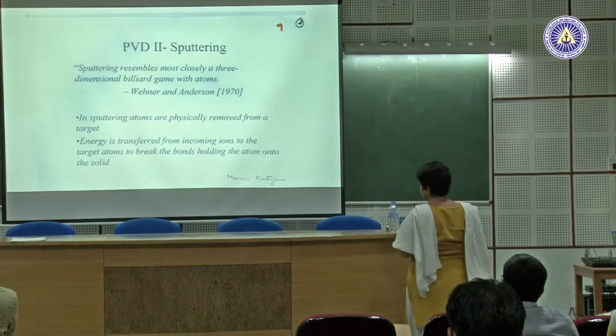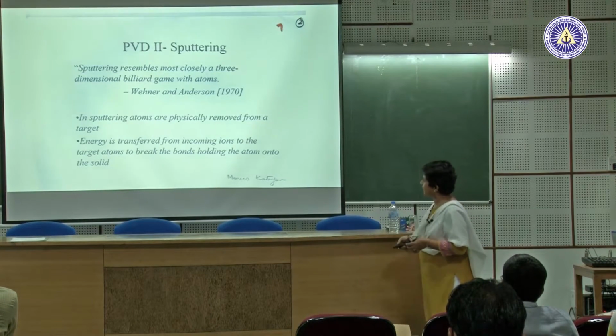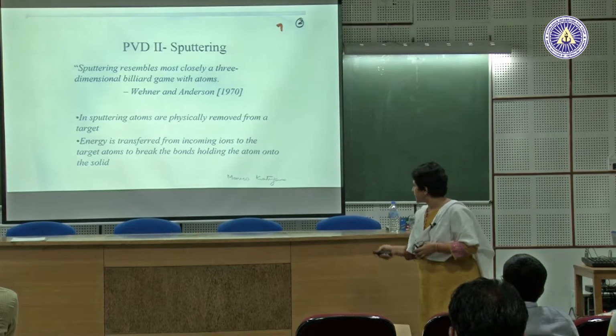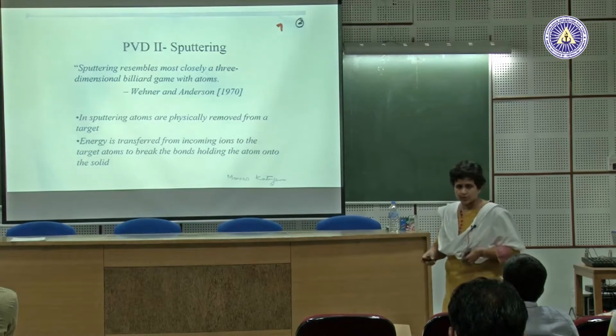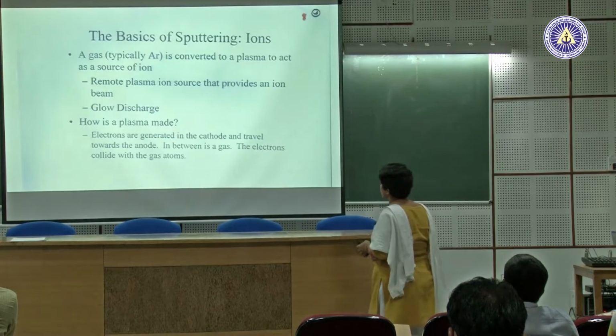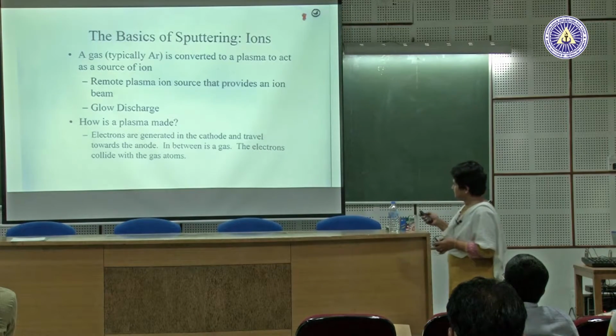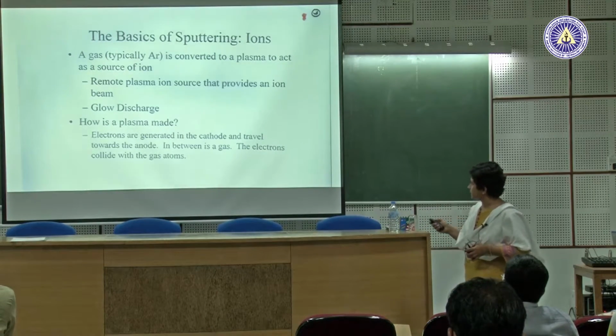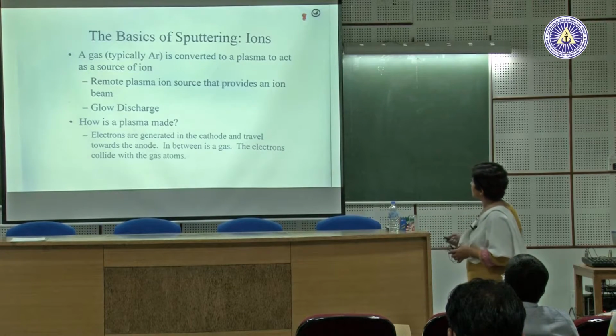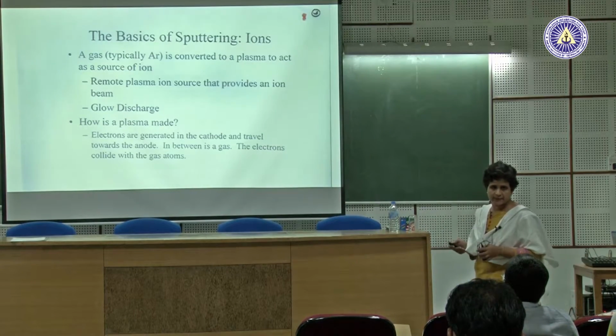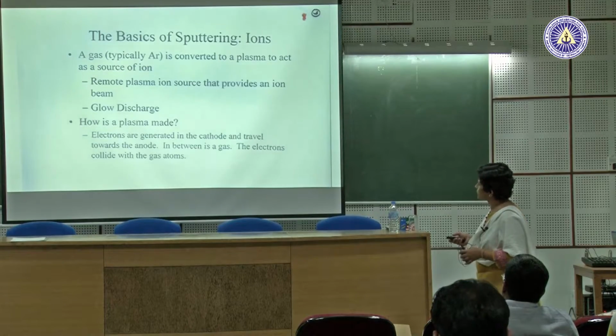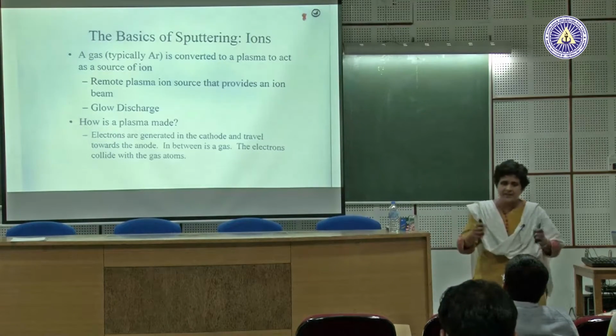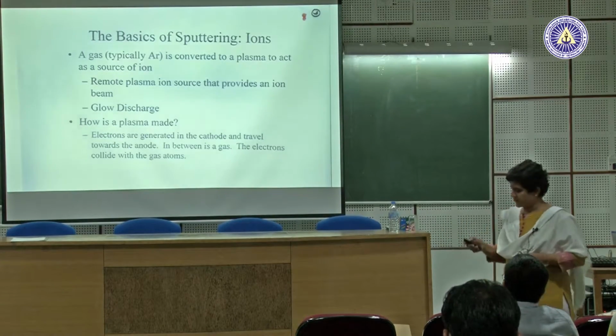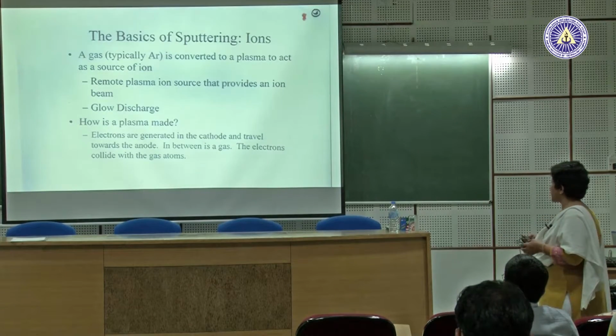So, atoms are physically removed, energy is transferred from incoming ions to the target atoms to break the bonds holding the atom into a solid. That is how the sputtering process is done. So, generally in the sputtering process, a gas, typically argon, is converted to a plasma to act as a source of ion. Remote plasma ion source can also be used, or you can just create the plasma inside the chamber itself. How is a plasma made?